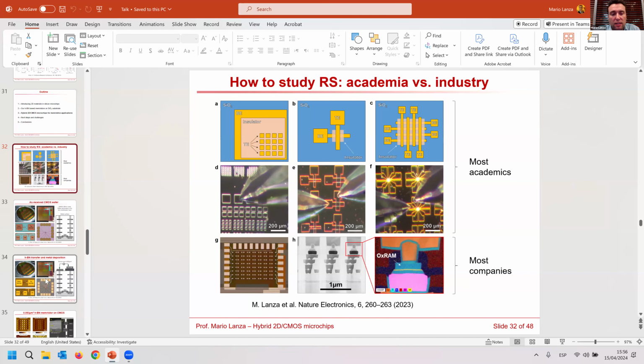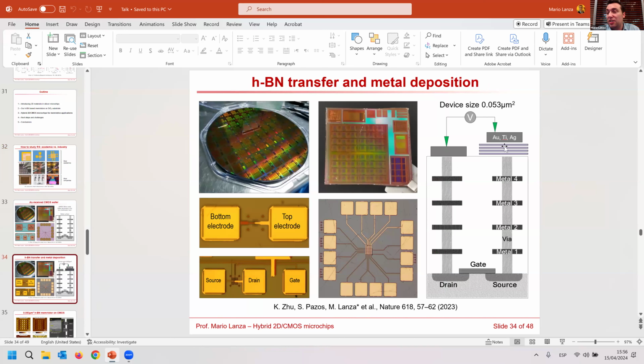But in fact, this is integrated at the last metallization layer. So there are papers and patents of other devices that use even iridium, which is even more contaminant, in the backend. Because this is not so close to the transistor, even gold here will be fine. Of course, it will not contaminate the microchip, but it will contaminate the chamber. But you can use it also, and it works as we demonstrated. But yes, you can use another, more friendly material, like aluminum or copper. But yes, it's completely CMOS compatible.